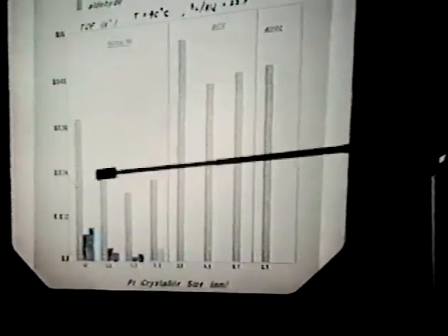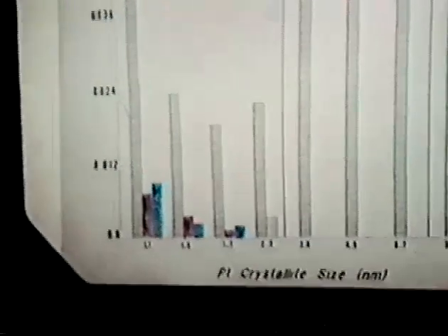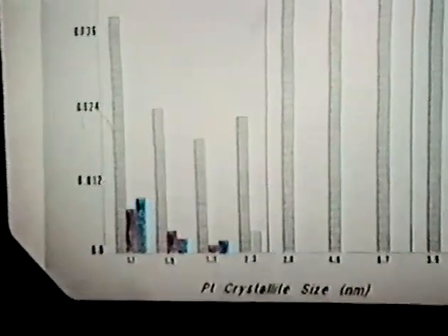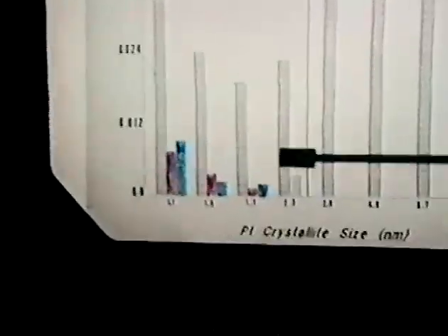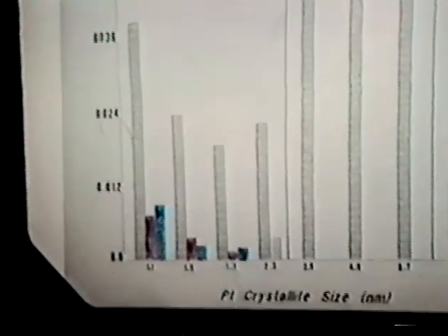However, this is the platinum on the low temperature reduced sample. Here for the first time we saw some capability for forming the crotyl alcohol. We had 4 different crystallite sizes of platinum present as determined by chemisorption measurements. They're not markedly different. They range from about 10 to 25 angstroms average particle size. But we see with this particular system, we have been able to achieve a maximum of about 13 mole percent crotyl alcohol in our selectivity.